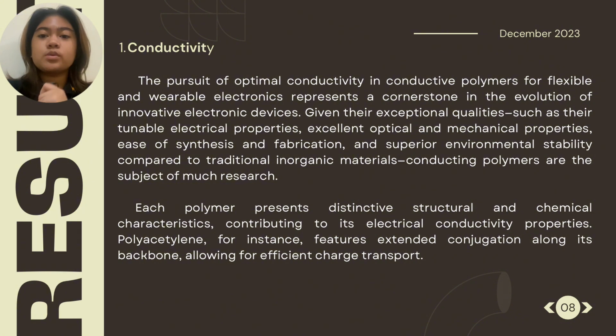Research by Ouyang 2018 highlights polyacetylene, or PA's, exceptional conductivity owing to its linear chain structure, with a conductivity similar to metals like copper and gold, up to 10^5 siemens per centimeter. PA's potential is remarkable. However, it's susceptible to rapid degradation in air due to oxidation, which hinders its practical use.